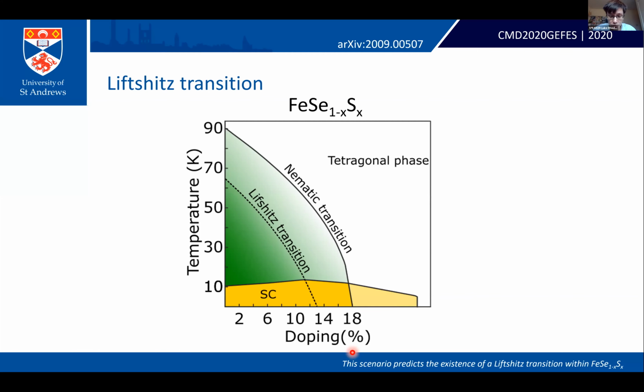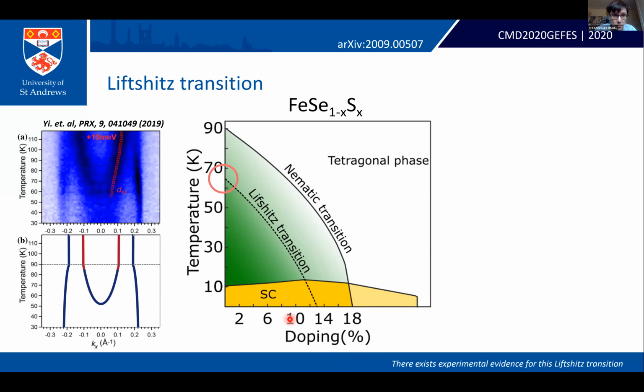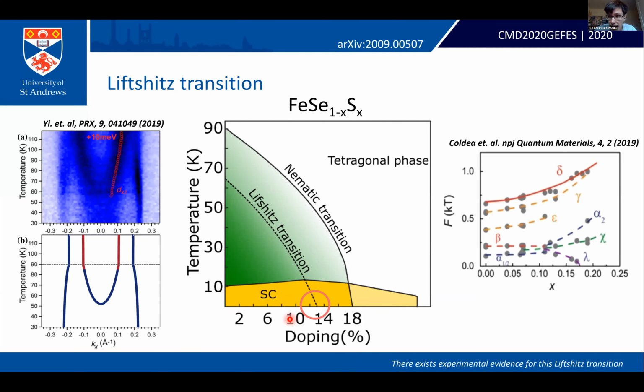Naturally, when we thought about this, we went and we looked in the literature to see if there was already evidence for this Lifshitz transition. And it turns out there is, both as a function of temperature and, in our opinion, as a function of sulfur doping. I'd like to focus on this sulfur doping data. This is the quantum oscillations data that Amalia Coldea presented earlier this morning, because I would like to show how this data is indeed fully consistent with a Lifshitz transition associated with a dxy electron pocket.